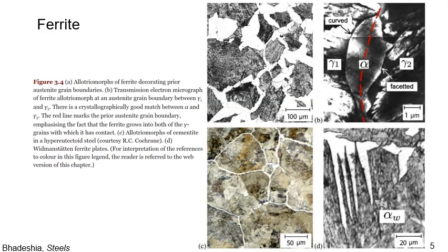So since ferrite grows first, let's talk about the different appearances or allotriomorphs of proeutectoid ferrite, grain boundary ferrite that can form. So up here in the upper left is kind of our familiar polygonal ferrite, where ferrite grows in kind of a blocky shape on the grain boundaries. And in this microstructure, the remainder internal to the grain formed pearlite.